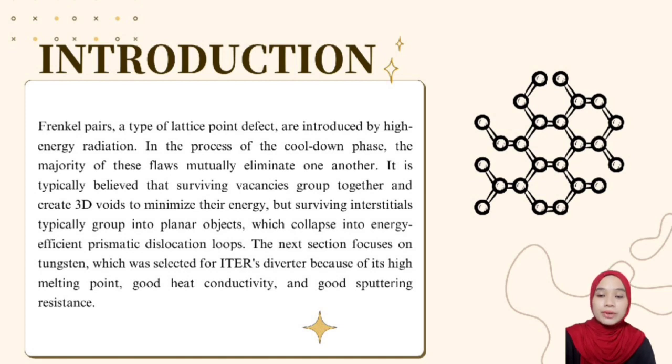The visible limit for voids in transmission electron microscopy (TEM) is approximately 1 nanometer. Researchers detected small voids in tungsten at the limit of TEM visibility that were created during irradiation at room temperature.